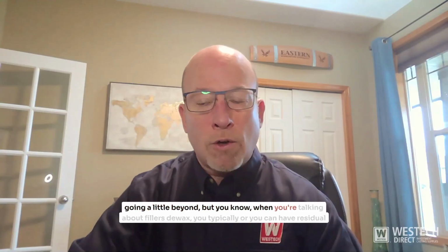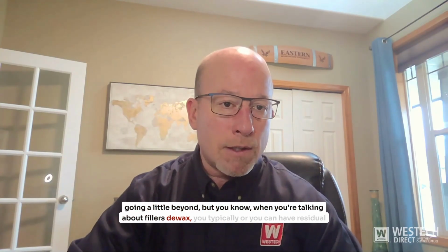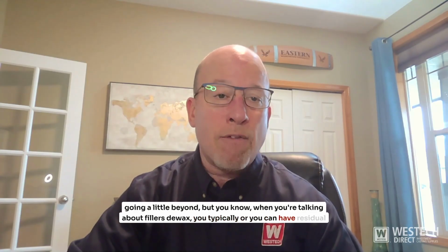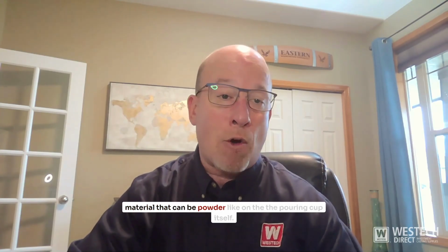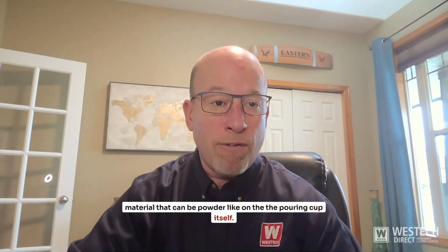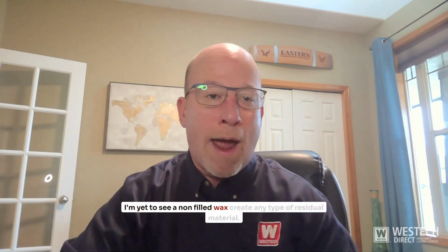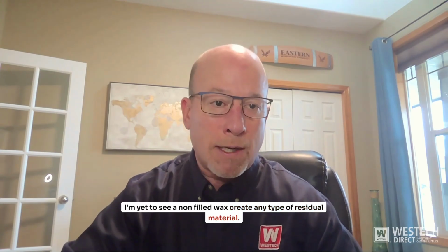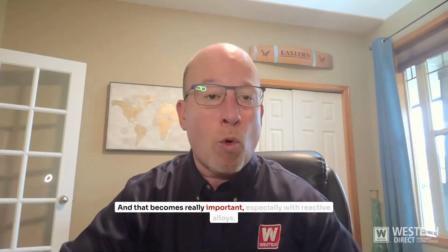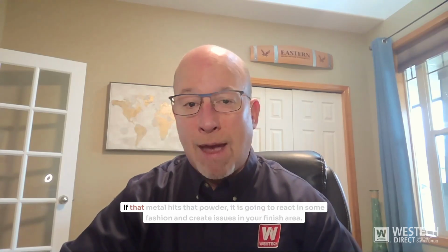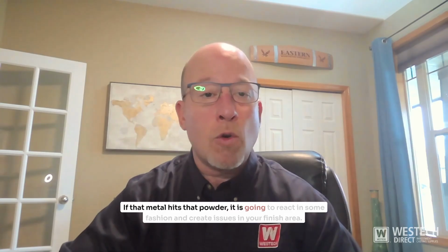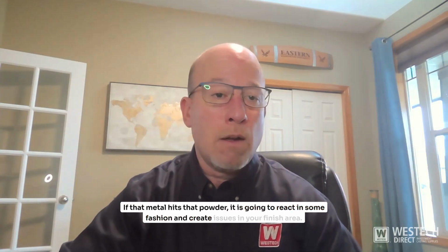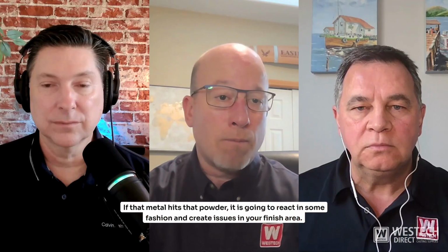So, once again, it's a cleaner process. That even includes residuals. And I know this is kind of going a little beyond, but when you're talking about fillers, at de-wax you can have residual material that can be powder-like on the pouring cup itself. I'm yet to see a non-filled wax create any type of residual material. And that becomes really important, especially with reactive alloys. If that metal hits that powder, it is going to react in some fashion and create issues in your finish area. GelSet 2.0 has no filler.